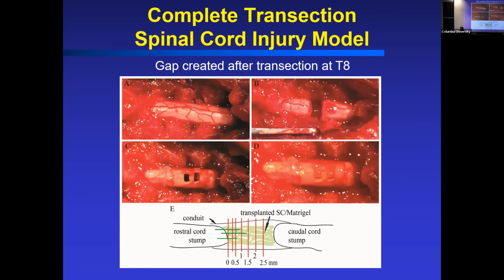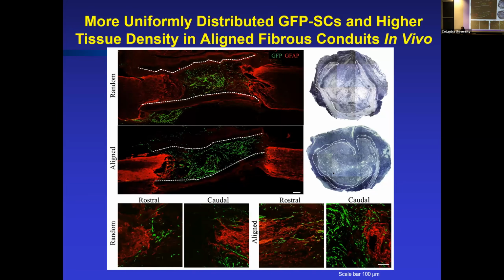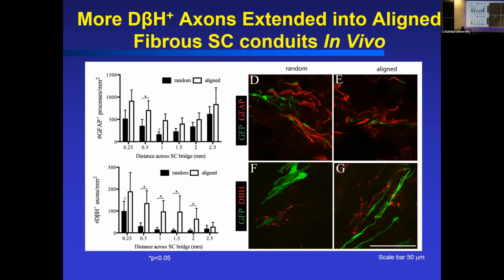I'm sorry I didn't give you a little bit of warning. There's a surgical image of that spinal cord injury model. It's a complete transection model that we've been utilizing to evaluate our materials. And here we implant those conduits, we add the Schwann cells, and what we find is that on those materials, that piezoelectric fluoropolymer, you're getting robust engraftment of those Schwann cells. The Schwann cells are the green. And you really don't see this kind of astrocyte or glial scar formation, very little in that defect when you implant these conduits.